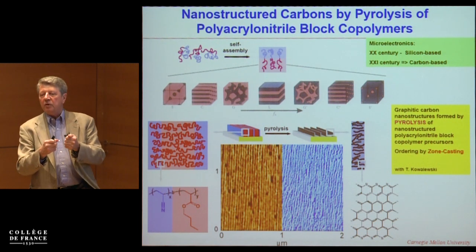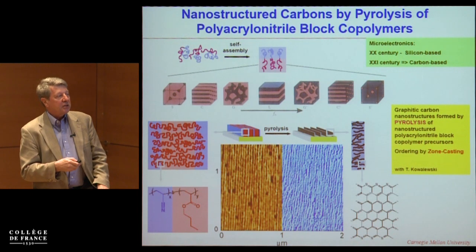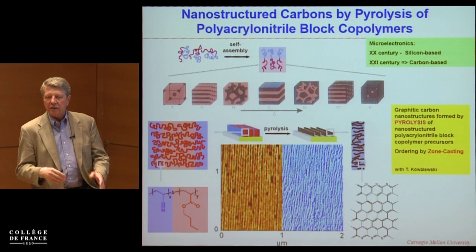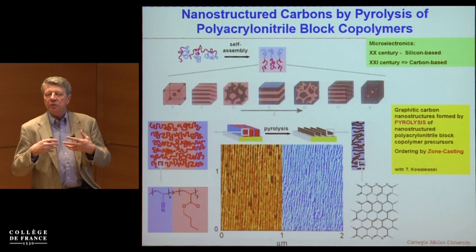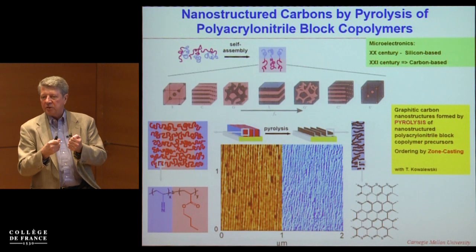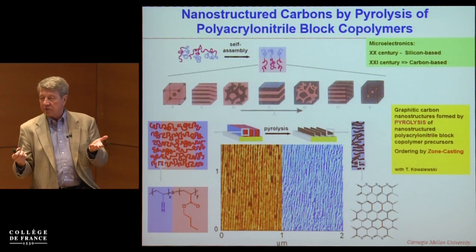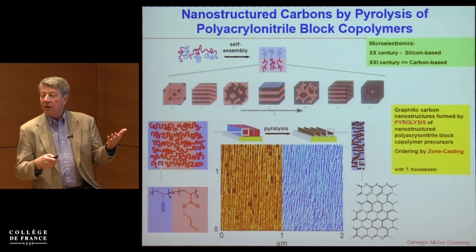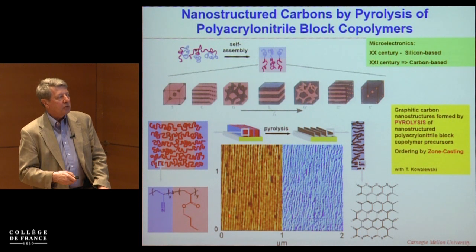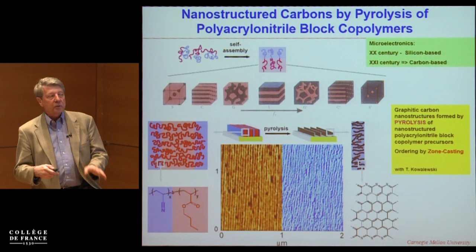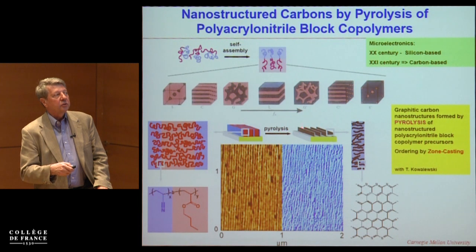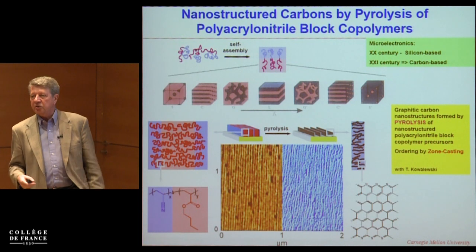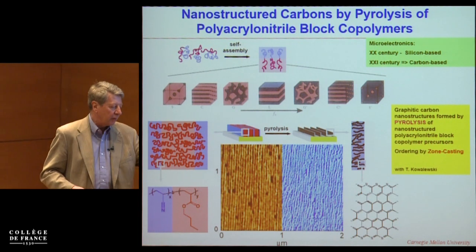So I need to fix the morphology at lower temperature, and this is done by cross-linking of polyacrylonitrile. I will explain on the next slide how it occurs, but this is something which spontaneously fixes this morphology, and it cannot go through the order-disorder transition temperature. Because of that, we really have the possibility of developing this structure. So at low temperature, they are phase separated. At higher temperature, we can have only this residue of carbon, because polybutyl acrylate will disappear as a sacrificial block at around 450 degrees.